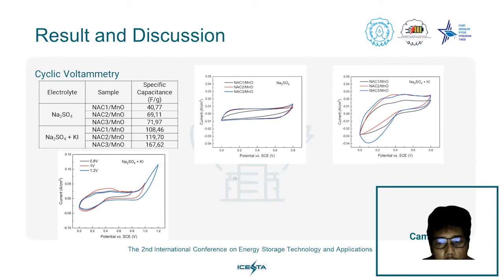It means that the electrolyte is decomposed. And we know that an aqueous electrolyte decomposes, there is a decomposition of water at 1.23 volt. So it means we cannot have a voltage of more than 1.2, so 1.1 to 1.2 here.